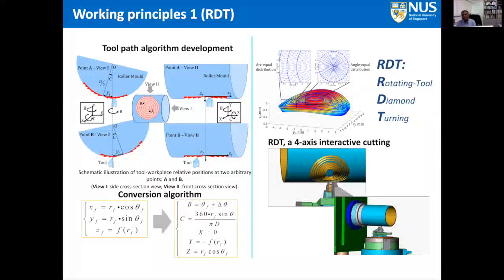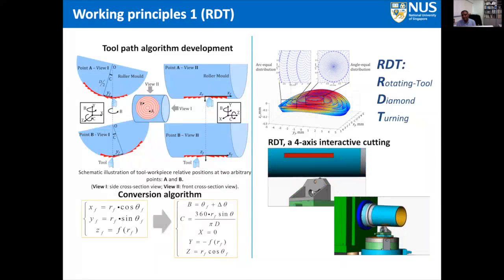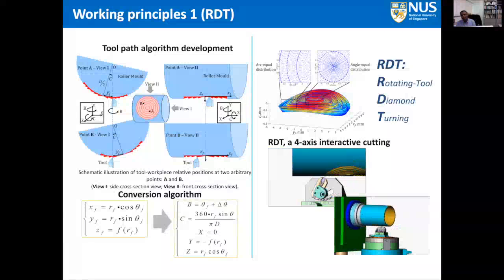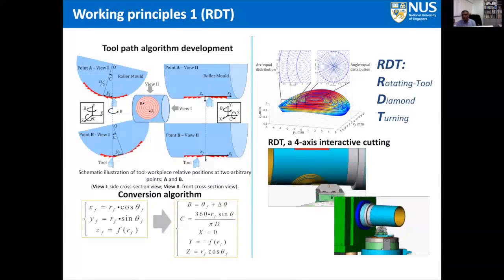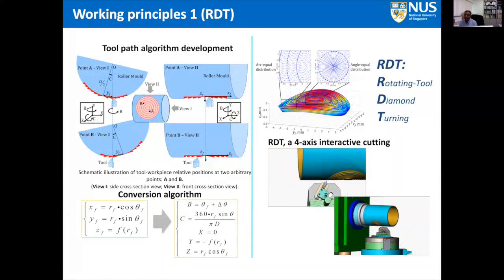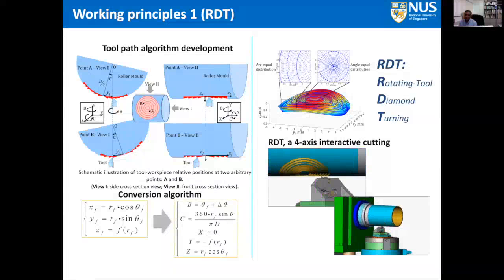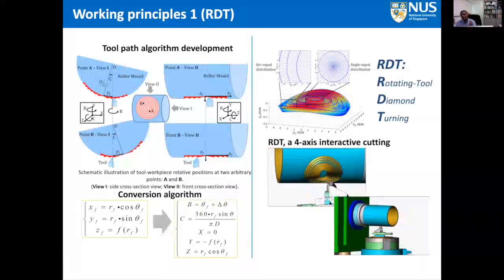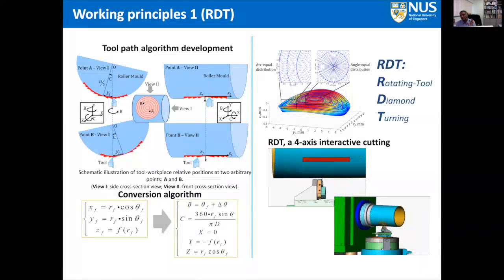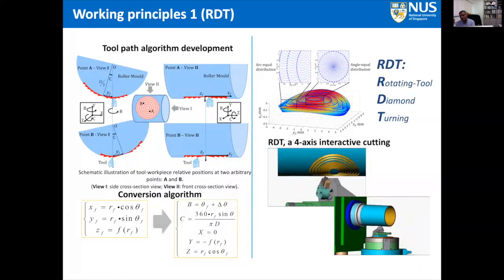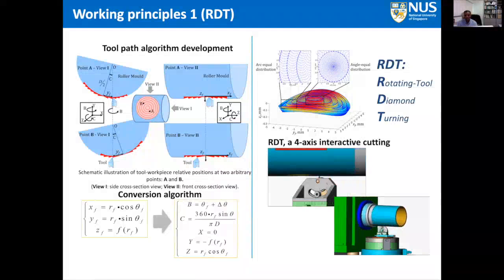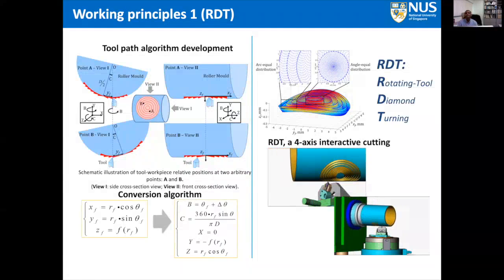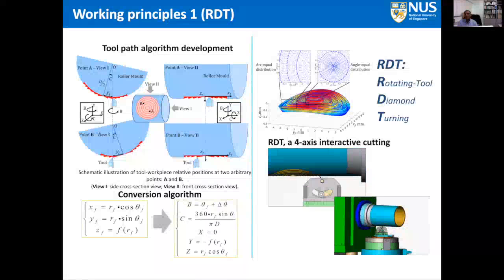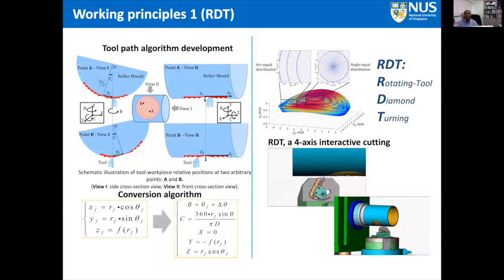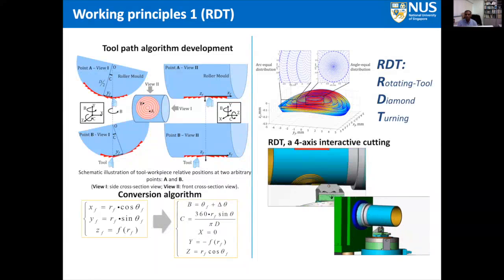So by continuously using the B axis in synchronization with the C axis, to ensure that a constant cutting angle between the tool and the roller surface can be achieved, we ensure that the depth of cut in the machining process is realized by the Y movement. Okay, so by synchronizing the movement of C and B, we are able to achieve the necessary features, and the depth is realized by the Y axis movement. By this process, we are able to achieve machining of very complicated features on roller molds.